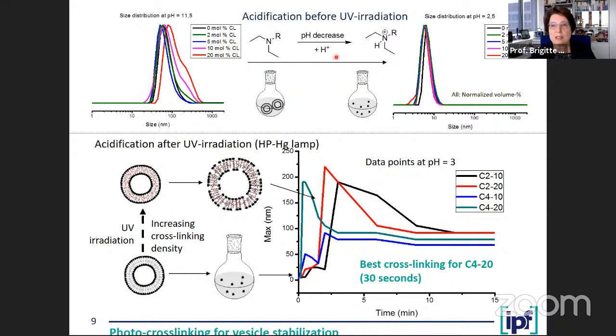So as soon as it's protonated, it's soluble. When you deprotonate it, it assembles. And of course, that goes back and forth. When you do it like we have shown here, we make the assembly and cross-link in the assembled state by UV. Then you finally get a cross-linked membrane and you can swell the membrane. It's like a hydrogel, but it cannot disintegrate.